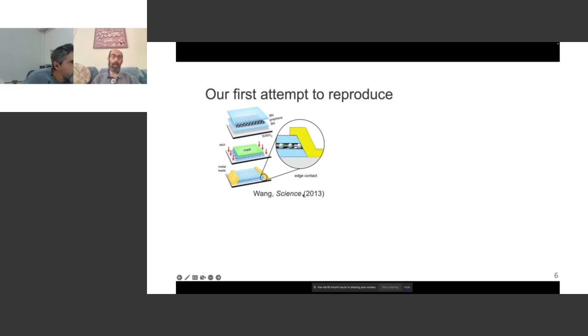This technique was developed at Columbia in 2013, and that's what we, and others, have applied to this twisted graphene layer with an extra trick: how do you make a controllable twist angle? You can take one piece of graphene, tear off half of it, and then rotate by a known angle and put it down on the other piece of graphene to get a known twist angle. So in any case,